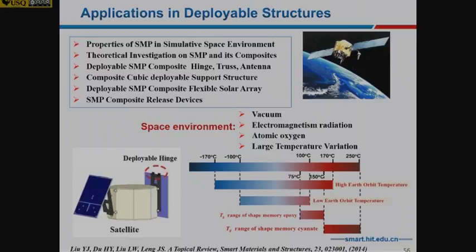But before doing that, we target the very harsh space environment. You have vacuum, radiation, atomic oxygen, and also temperature variations. Here is the satellite, and this is the deployable antenna and also the deployable hinge, which normally uses an explosive bolt. For low Earth orbit, normally the temperature is from -100 to 100. For high Earth orbit, normally we talk about -170 to 170 degrees Celsius. So that's why we develop different polymers to adapt to different temperature ranges.